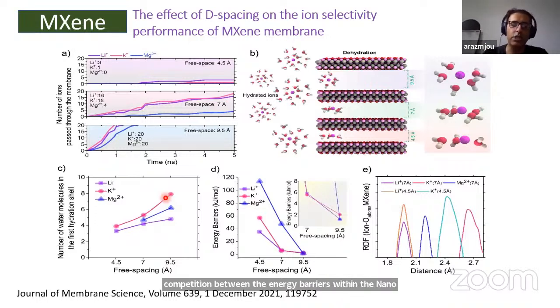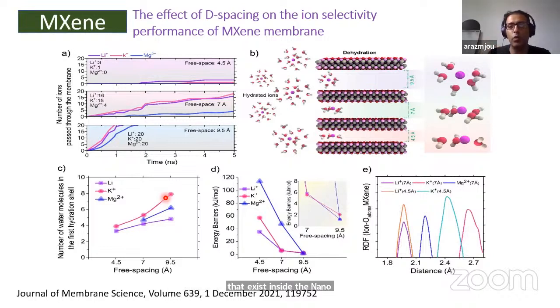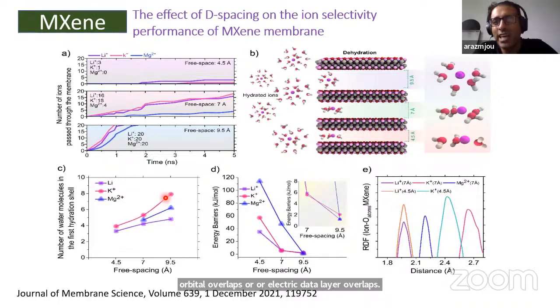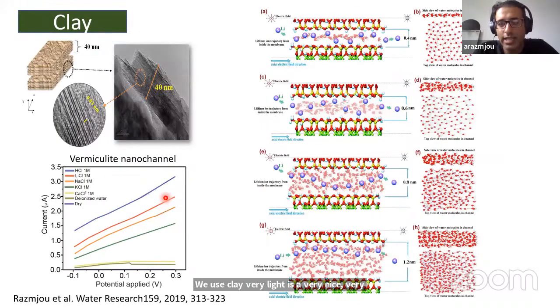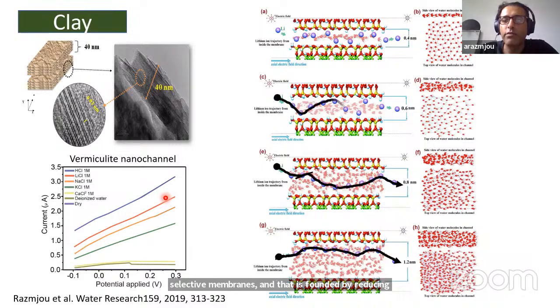There is a competition between the entry energy barriers of the nanochannels and the energy barriers that exist inside the nanochannels because of the orbital overlaps or electric double layer overlaps of the nanochannel surface walls. In another work, we use clay. Vermiculite is a very interesting 2D nanochannel that can be used for making nanoselective membranes. But we found that by reducing the nanochannel size, lithium ion transports in a zigzag fashion.